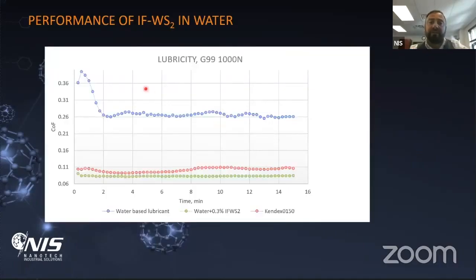If we look at the lubricities, right now it's a different test, it's G99, a ball on disc, and we're comparing the commercially available water-based lubricant and friction on that. So it's quite good compared to water, of course, but it's a water-based lubricant, so it has some polymers in it, some friction modifiers. So that's the friction over here. It's going up and then goes down due to formation of the tribofilm, due to polishing the track, because you can imagine the ball is rotating on a disc and the surface getting worked. So the friction may go down due to that as well.